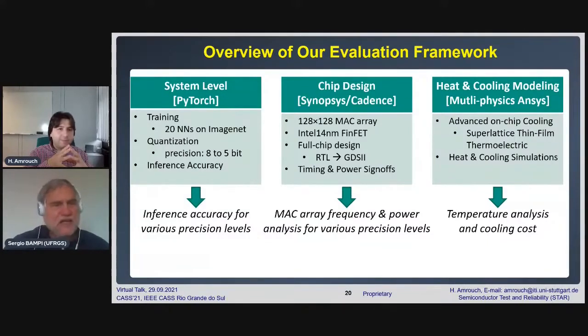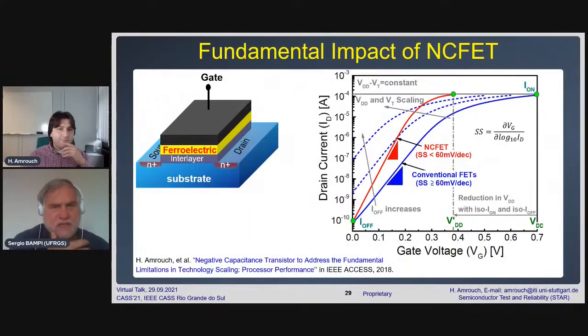Okay, in slide 29, you mentioned the advantage of having a steeper slope on subthreshold. But it seems to me that they still have not got the red curve in this picture having the same ion current as the conventional FinFET, the blue curve, and that's a problem that has been hindering the adoption of those transistors, just because the ion current does not go as high as we'd like. So what's the status of this development for the negative capacitance FET, which I know you've been working on for many years and published very important work on? But from the device side, are they getting good enough ion from actual devices?